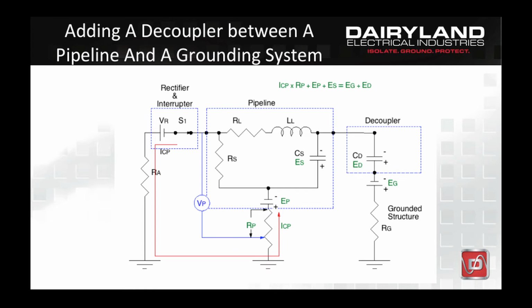Next, I am going to expand a pipeline schematic to include a decoupler. This example represents a typical application, such as where a decoupler is connected between a pipeline and a bare grounding system, typically zinc or copper in an AC voltage mitigation application, or just copper if providing AC grounding of electrical equipment in a pipeline. The new circuit elements that have been added are the capacitance of the decoupler, labeled C sub D, and a grounding conductor which has a corrosion potential of E sub G. This grounding conductor has a resistance to remote earth represented by R sub G.